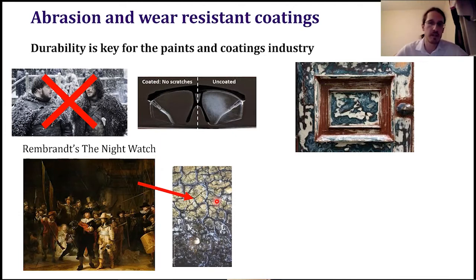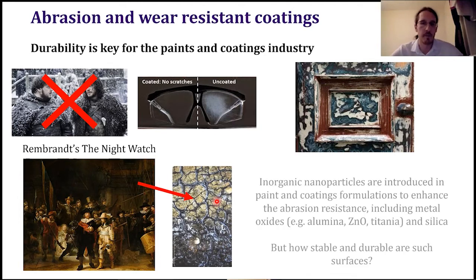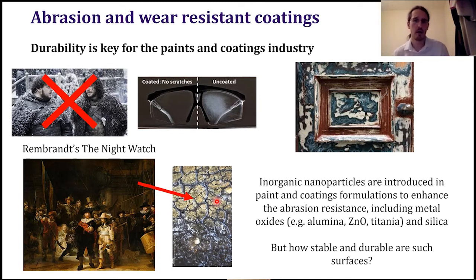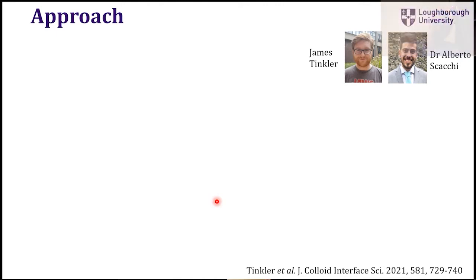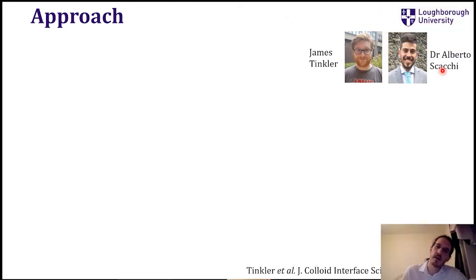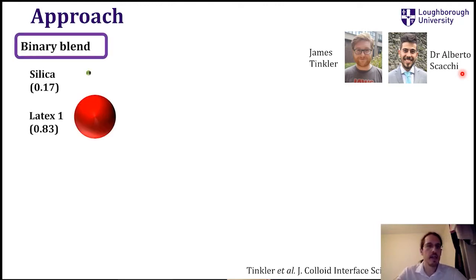So we need something that protects it. One of the things that is quite used in the paint industry is the use of silica nanoparticles or metal oxide. So we thought we can try and see whether we can design some coating that resists abrasion using silica nanoparticles. In particular, this is work from my student James and also Alberto, who did some modeling, which I will show you now. So the idea is we start with a binary blend, which is just two sizes. We have our small silica particles and our large latex particles.